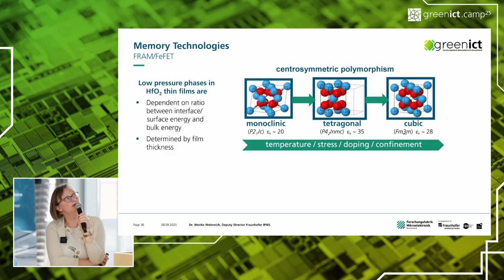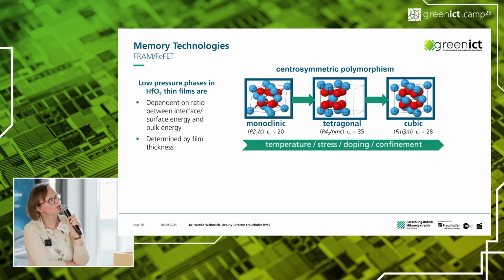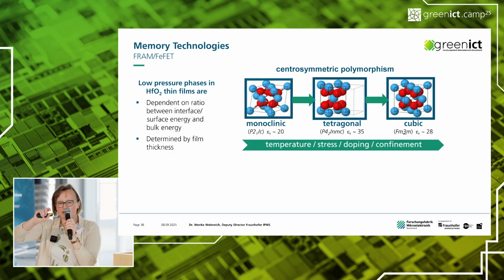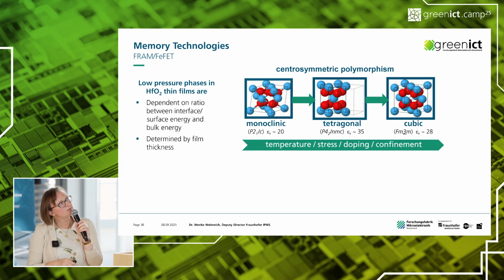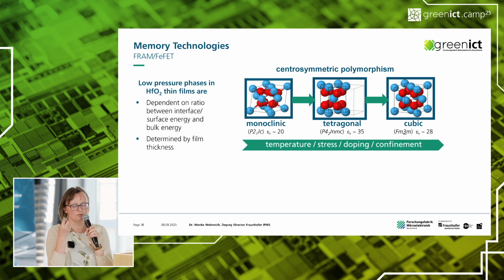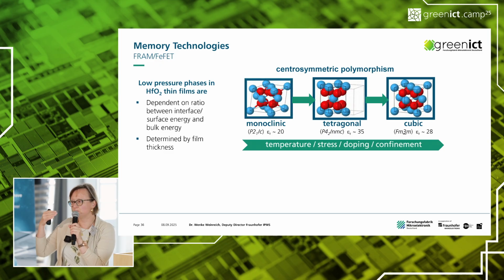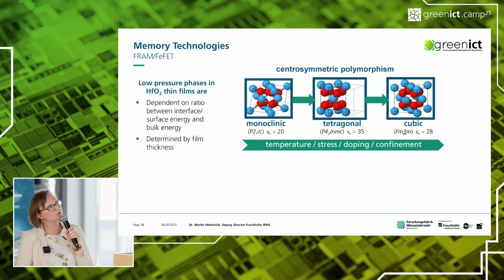Why is this the case? So why is hafnium oxide ferroelectric? Because that was not expected, really not expected. Normally, if you build this hafnium dioxide in the gate, from 1 to 10 nanometers at the beginning, this material in thin films only has symmetric phases. So the crystal structure of hafnium oxide in a normal case is symmetric. So you would never have any polarization inside because it's only symmetric phases like monoclinic, tetragonal, and cubic.